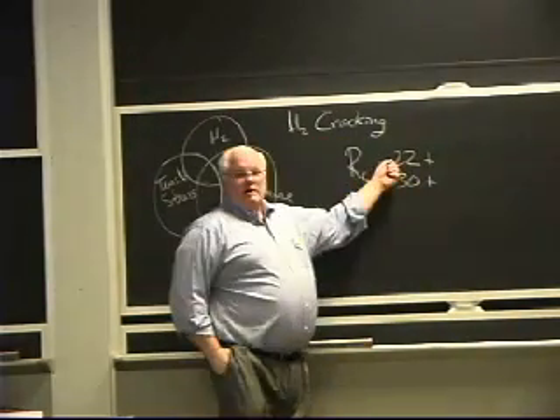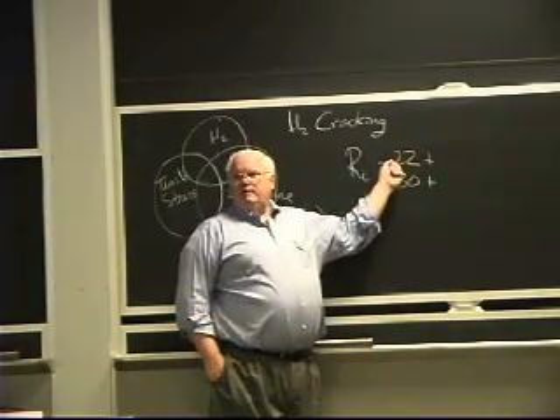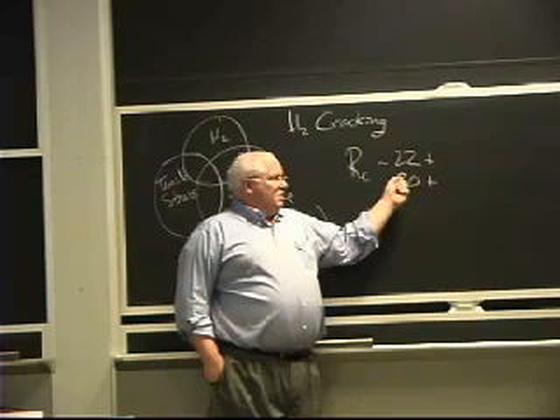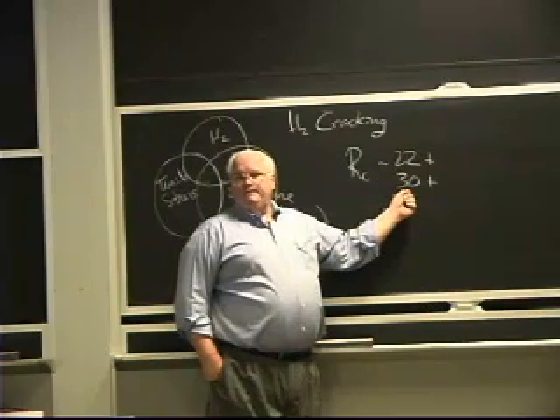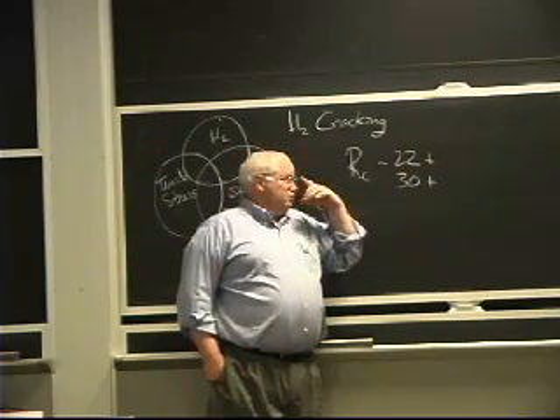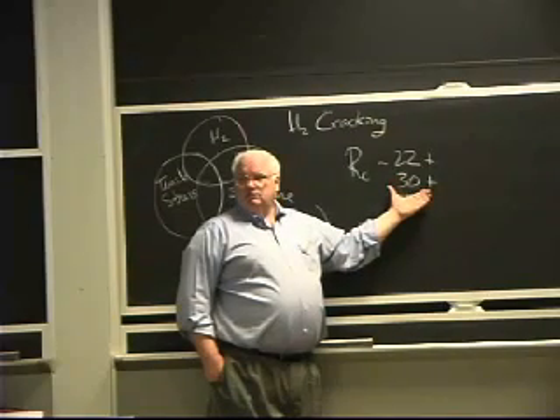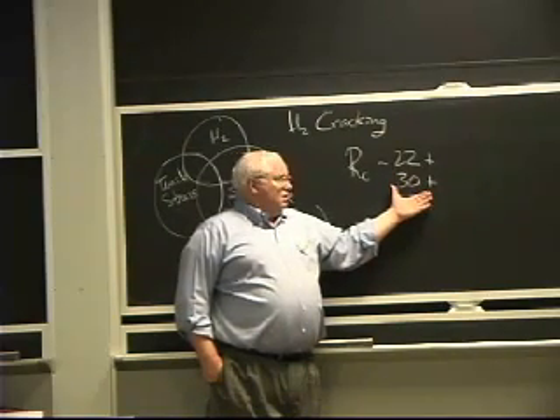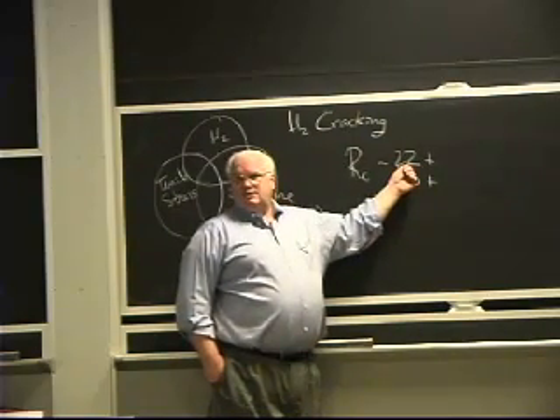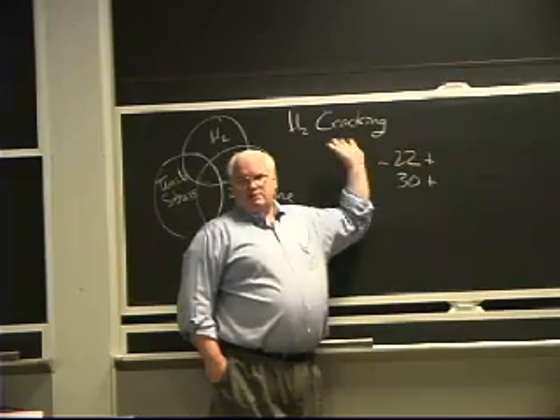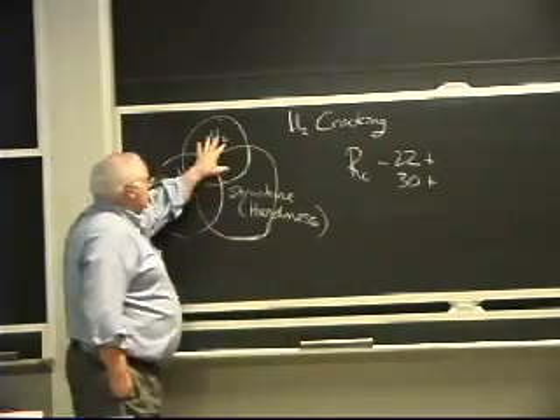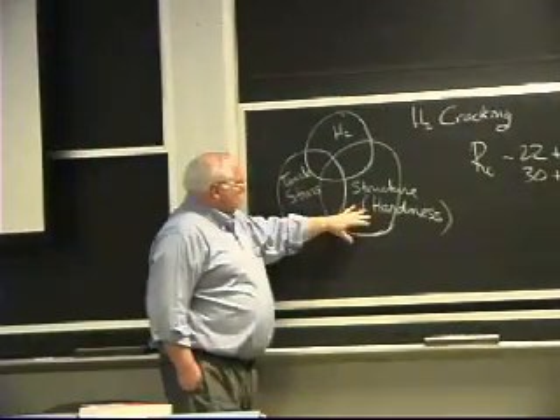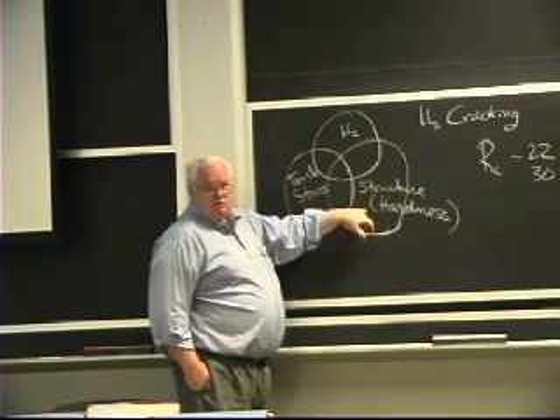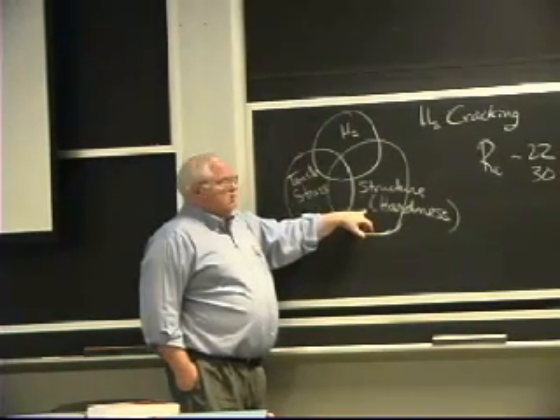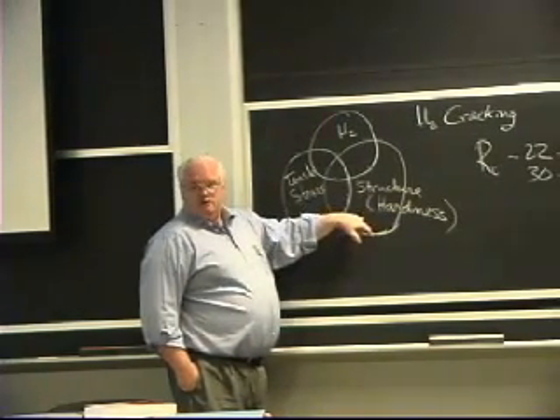If I'm in the pipeline industry, I don't want to see a hardness above 22, Rockwell C. And if I'm in high strength steel business, like 100 KSI steel would be Rockwell C30. The reason for this is, turns out it's hydrogen sulfide cracking, which is just another form of hydrogen cracking. So you have to have a source of hydrogen, a source of stress, and a susceptible structure. Well, steels, depending on their composition, will give you various amounts of hardness.